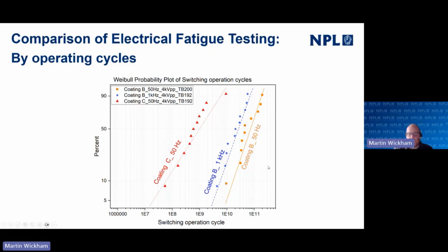So if we plot that as switching operations, you can see that there probably isn't much difference, certainly with this coating B, between the 50 hertz and the 1 kilohertz. But there's still enough to suggest to us here that the 1 kilohertz is failing earlier than the 50 hertz. This may be because there's some corona discharge happening in this sample, which is damaging the plastic coating more readily than it does at 50 hertz.